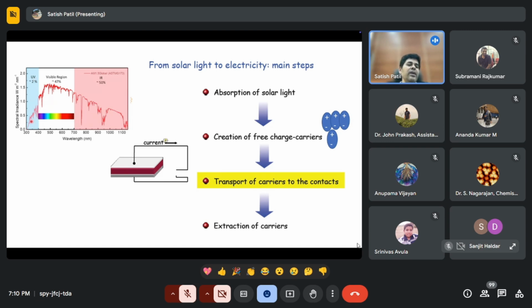Even this range of photons also damages organic semiconductors, because the energy of these photons is very high. They can cleave the bond between carbon and hydrogen, or carbon and nitrogen, carbon and sulfur. So these are not really useful light when you are making a photovoltaic device. You do not want a material to absorb in this part of the wavelength, and you do not want this to be at very high intensity. As I mentioned, this is the solar emission spectrum. The majority of the light comes in the visible part of the spectrum, 400 to 700 nanometer. This is a 47% major component of the spectrum.